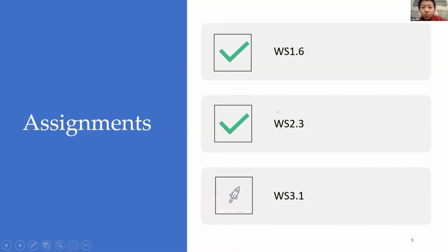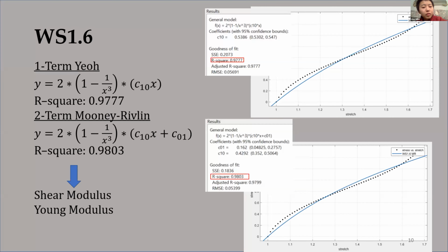As far as the assignments, we unfortunately were unable to accomplish assignment 3, but we look forward to doing this in the future. And we're very appreciative of the opportunity to have all these assignments. For the first assignment, we used the first-term Yeoh and two-term Mooney-Rivlin to analyze the material. With this, we found that the R-squared fit of the two-term Mooney-Rivlin was more effective. And from these, we were able to find the shear modulus and Young's modulus for choosing the elastomer.